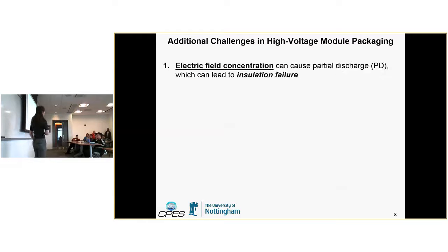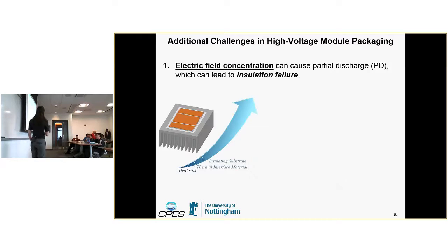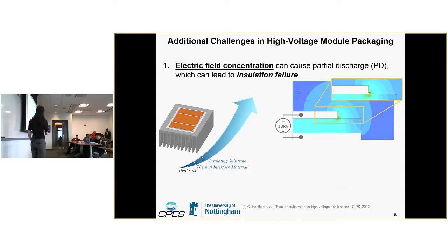Now you also have to worry about electric fields. I mentioned this briefly before, but in particular, if you have a very high electric field concentration, you can get what's called partial discharge, which is a very high energy event. If you see it, you can actually see it. It's a spark that occurs, and you can even hear cracking in the air when it's breaking down air. This is primarily a concern in your insulating substrate, which does the majority of the blocking of the voltage in your power module. This is a cross-section look.